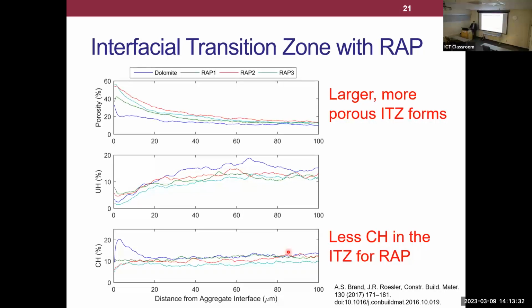What we definitely see for RAP, I thought I had it highlighted, okay, we have RAP up here, we have porosity. This is distance away from the aggregate surface, so the aggregate surface is at 0. Here's dolomite, that's our virgin aggregate, which is just calcium magnesium carbonate.